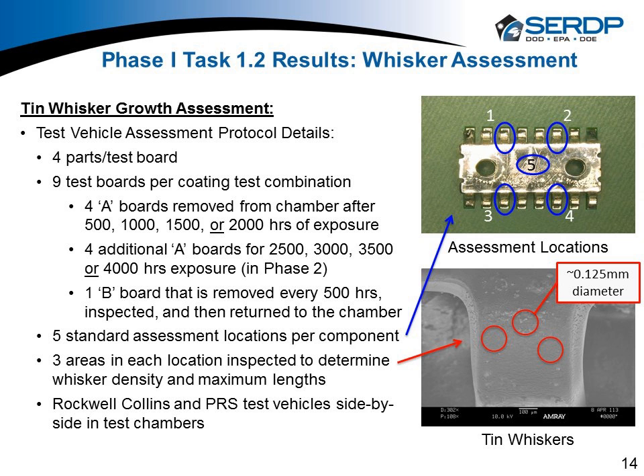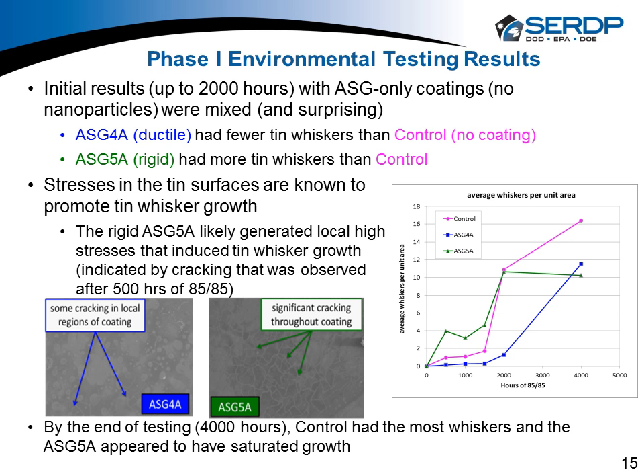if any differences there. When we did look at these specimens, and we got down to looking at each of the 5 areas, we would go in and measure 3 different areas on here randomly. It's a 0.125 millimeter diameter, and we would measure lengths and measure whisker density. And that's how we were tracking what was happening between the different variables in the design of experiments. To go to slide 15,